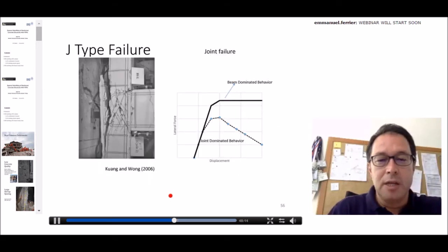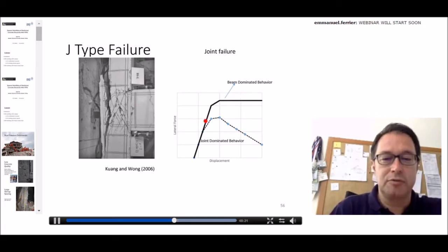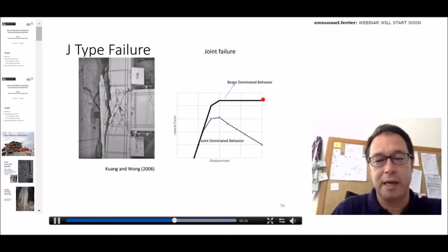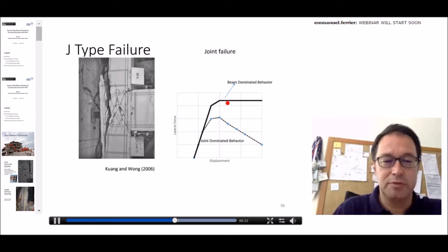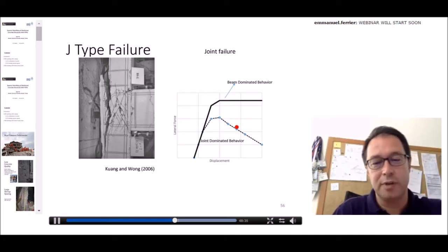So if you look at J-type failure, where we have the joint failure itself, if we didn't have this kind of problem in the joint, or if we have sufficient joint strength, then the behavior would be like that. But in case of domination of the joint behavior, then we might have this kind of behavior, which is reflected by a lower strength as well as a significantly reduced ductility.